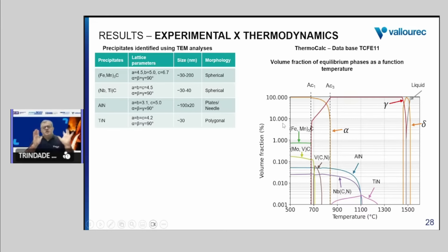Okay, so we compare what the observation shows with the thermodynamic calculation. In this case, we use Thermo-Calc software, and we can see that in this low temperature region, where the material is submitted to tempering and aging at 250, the expected thermodynamic precipitates are very close to what we have observed in the experimental study.